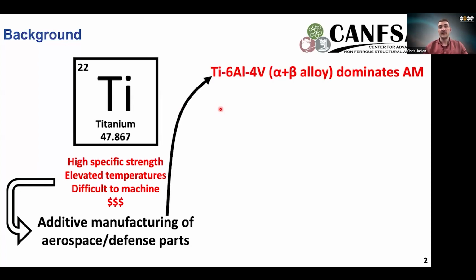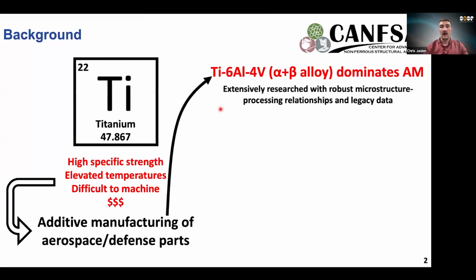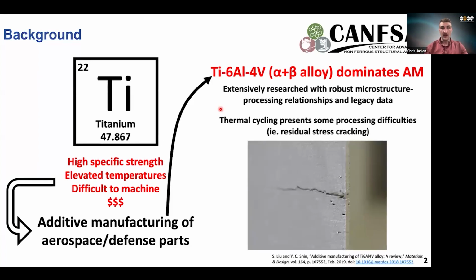There's one alloy in particular which has really dominated the research space and exploration. That is officially called Ti-64, 6 weight percent aluminum, 4 weight percent vanadium, and that is classified within the titanium world as an alpha plus beta alloy. It's been extensively researched. There's a good understanding of how you process it, how it is going to react at the atomic level, as well as at the mechanical property level. However, with this material, there have been some problems.